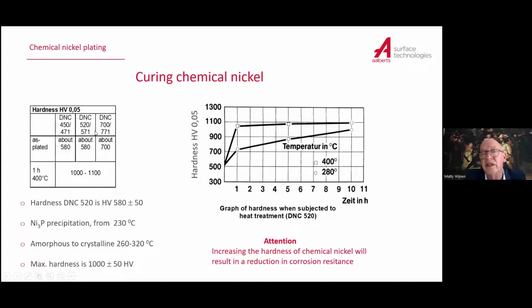And that's done by using temper ovens with temperatures between 280 to 400 degrees. And beware, this will always have an influence on your materials. So if you say, okay, I want the chemical nickel on aluminum, but I want to have it hardened in a short time, so say 400 degrees, you can be sure that your aluminum has lost more than half of its strength. And that's something you have to take into account. If you want to increase the hardness by chemical nickel heat treatment, you have to make sure that the material you use is suitable for that. And also hardness increasing will result in a reduction in corrosion resistance.